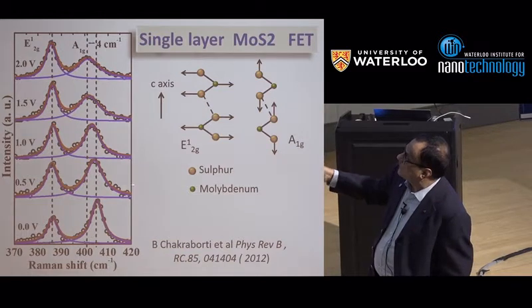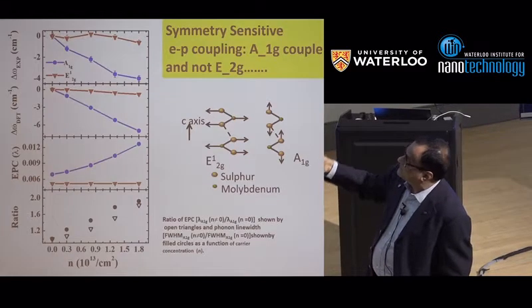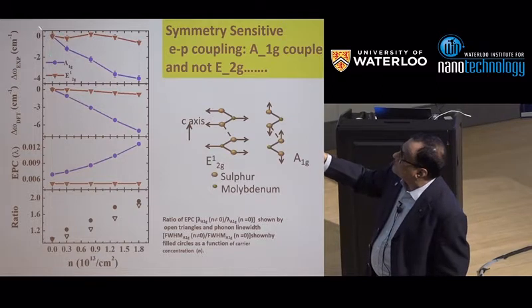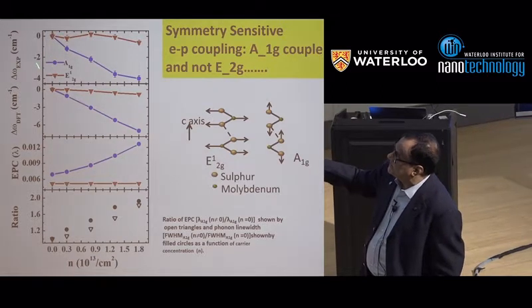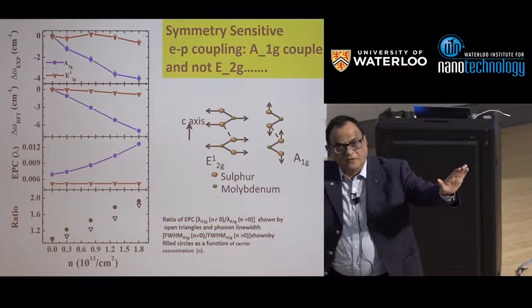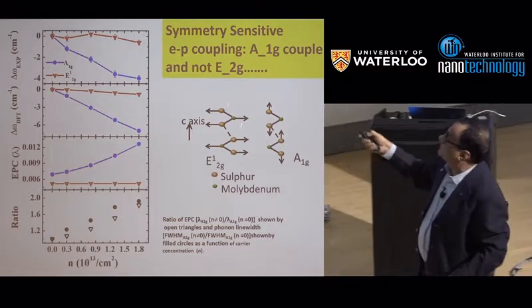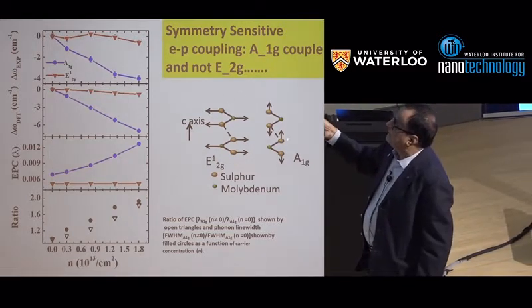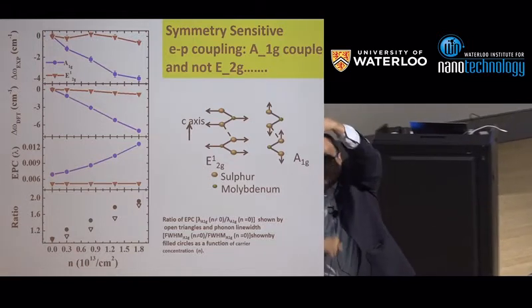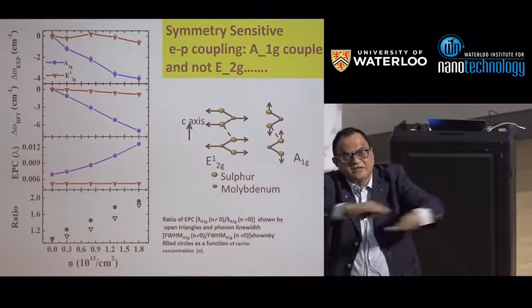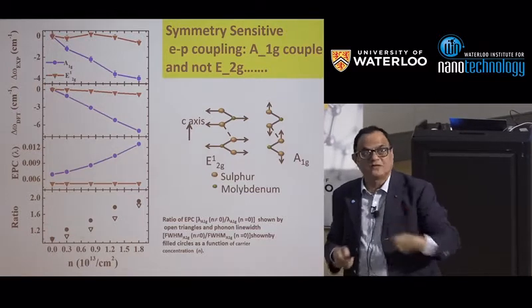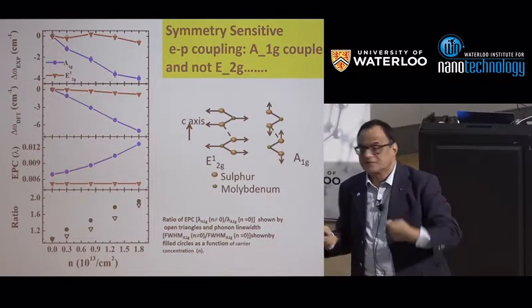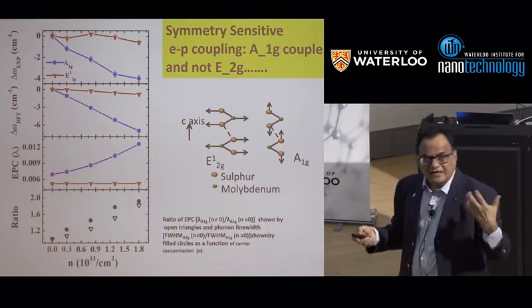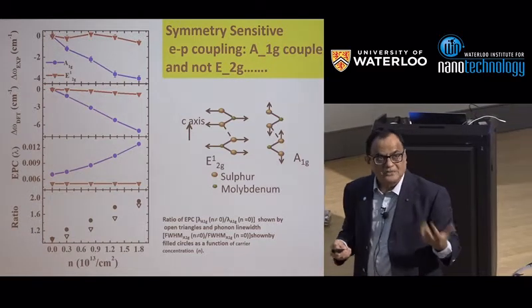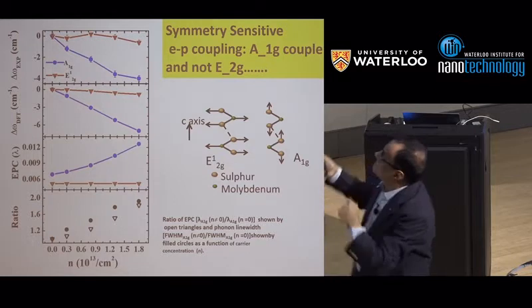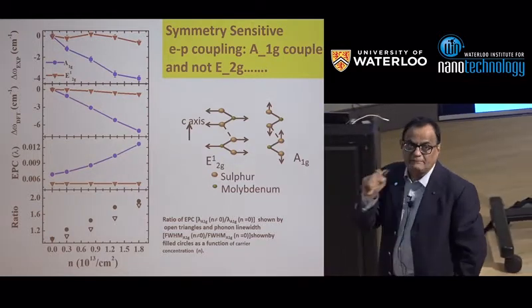And what we have shown at that time, that if you make a similar device, only the A1G phonon is affected, this frequency, and nothing happens to E2G phonon, because these phonons have different ways of vibrating. A1G phonon has atoms moving out, and E2G phonons are in plane. Now this again you can go to theory and compare with experiment. This is what we did, and you can again get a quantitative number on this interaction. Now this interaction is symmetry dependent. This is the message of this.